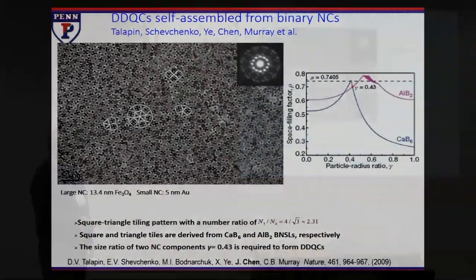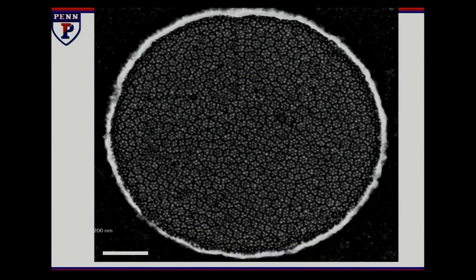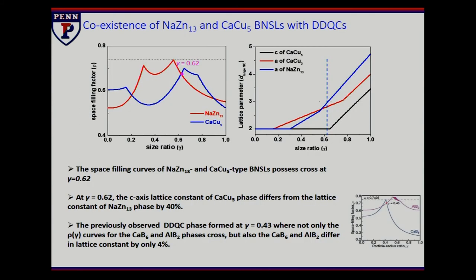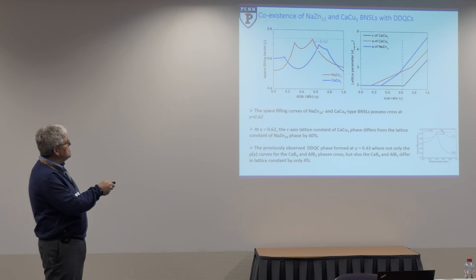All right. So if we go to that one, I will go back to the quasi-crystal part because I just like that piece. Okay, let me go to one piece. So if we take a system where we mix two components and they want to form superlattices but of incompatible symmetries, so one wants to be cubic and the other wants to be hexagonal. If you left them on their own, they would naturally go towards those two systems. But if you choose a size ratio where you frustrate them, they basically don't know which way they want to go. So right at this point, there's a crossing in terms of the density so that the two structures are nearly identical. And then you have a curious competition. You could get nucleation of separate phases if they're able to move far enough away from each other. But they also could solve the problem by trying to preserve local symmetry as they pack.